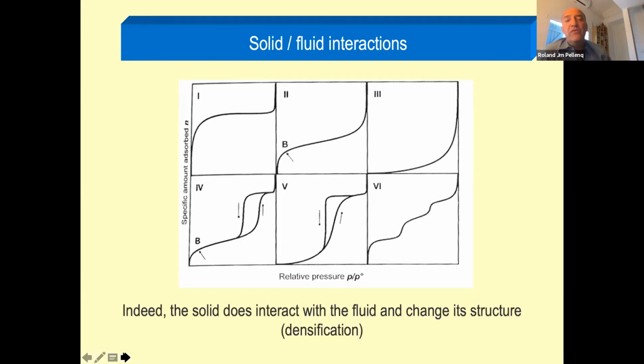And then we have number 1, the so-called Langmuir adsorption isotherm, which typically happens in very tiny pores where there is not much fluid-fluid interaction. Everything is driven by the fluid and the surface. This typically happens in zeolites, porous carbons, and so on. And the way up is equal to the way down, so there is no hysteresis loop.